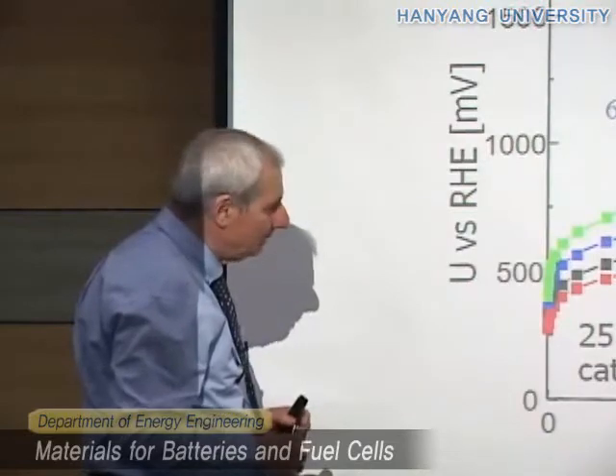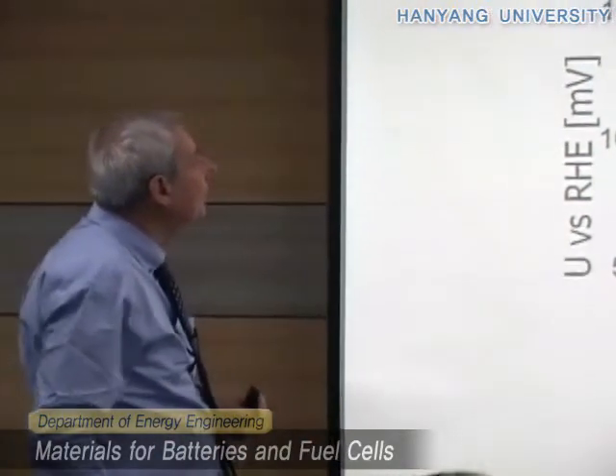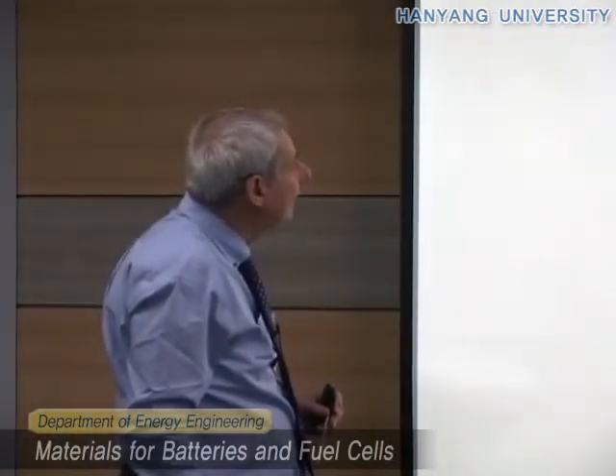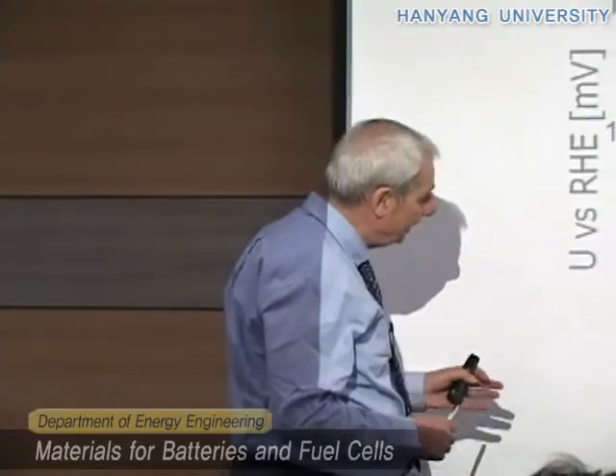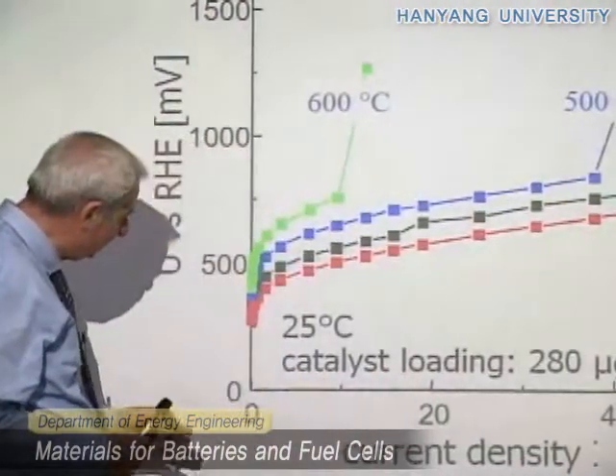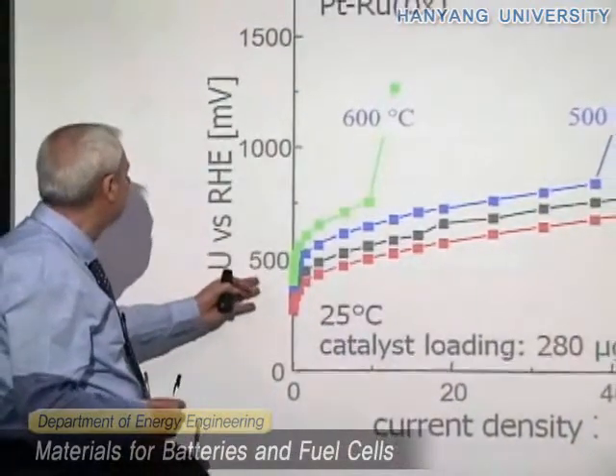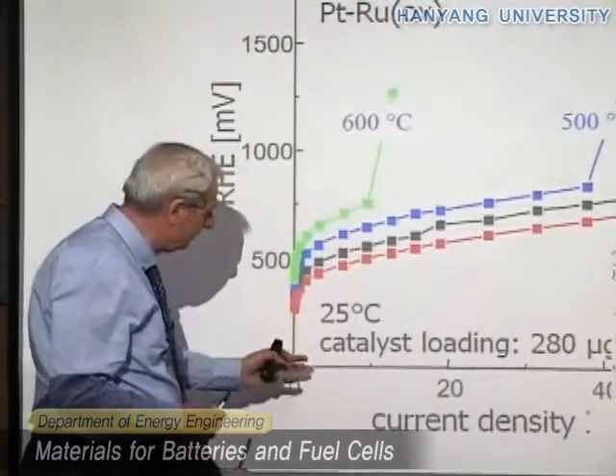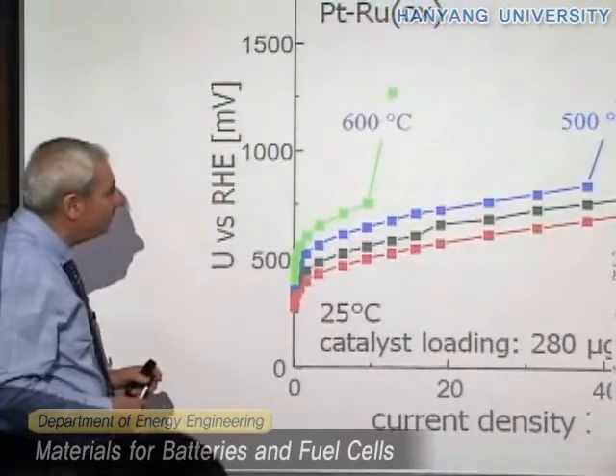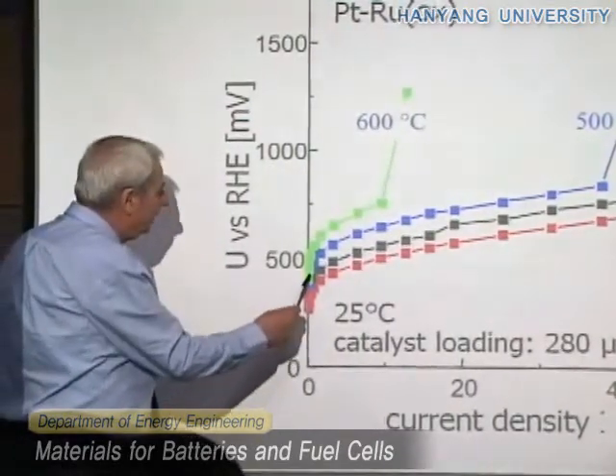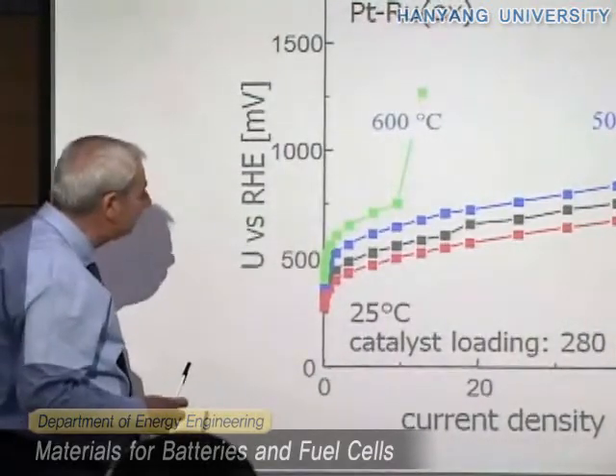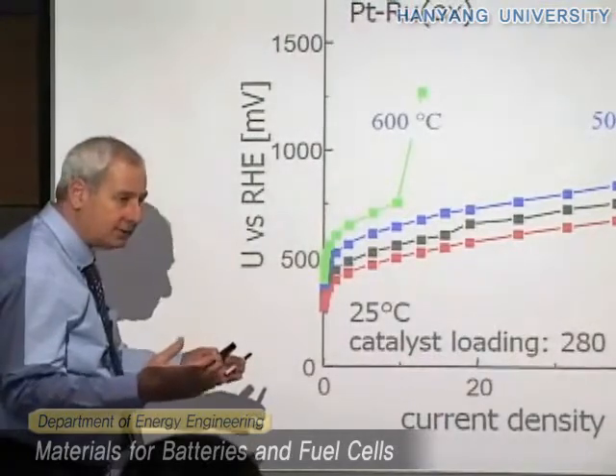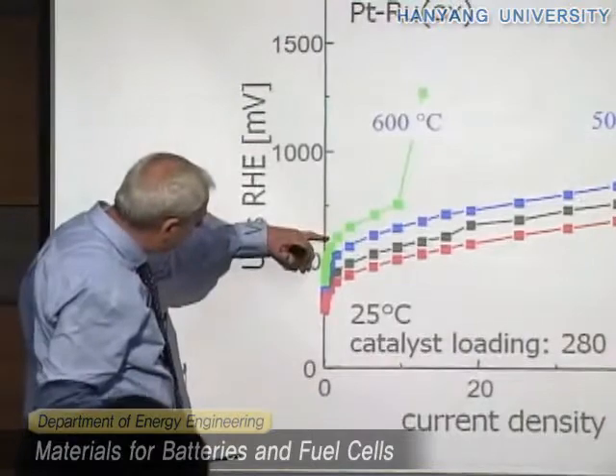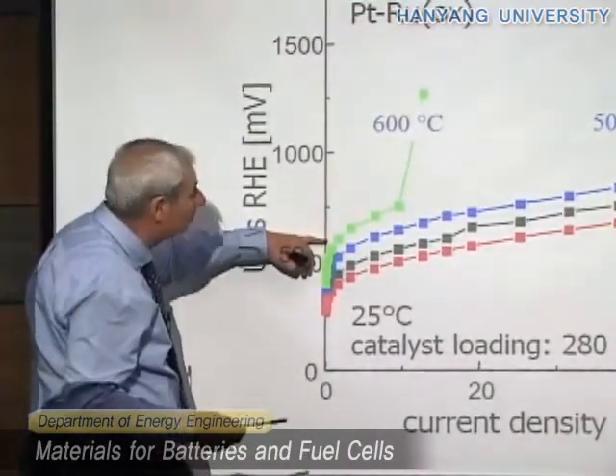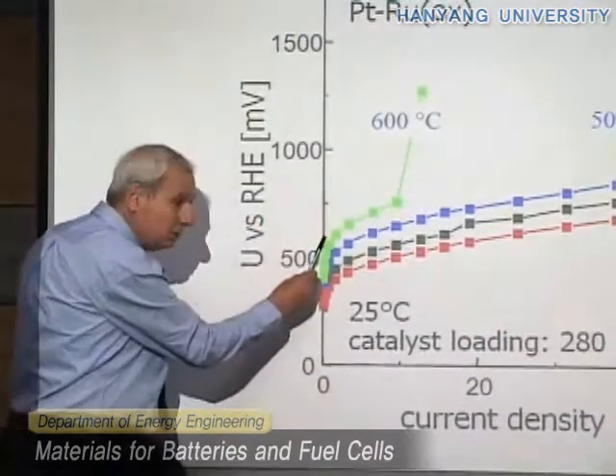But you must be a little bit careful here, because when you prepare your catalyst, you can do it under different temperature conditions. Here is reported a typical curve which gives you the current density versus the potential, and the loading is the same for all these three cases. And you see that for the case when you prepare your catalyst at 600 degrees, because this is prepared with a solid state reaction, you have the voltage at which we have oxygen evolution. I think this is due to oxygen, this value, okay?